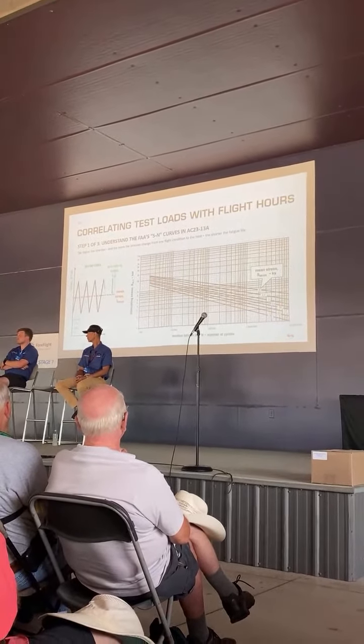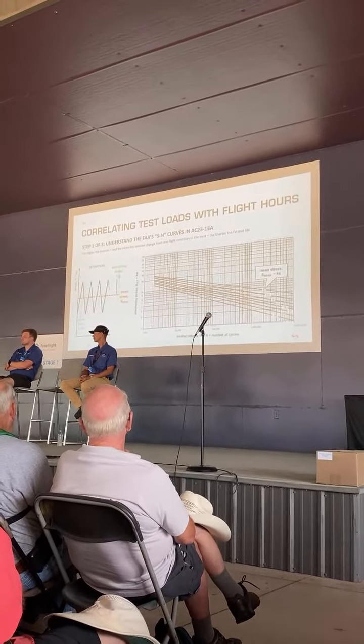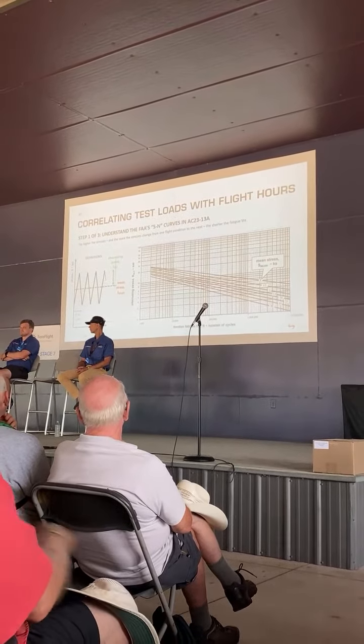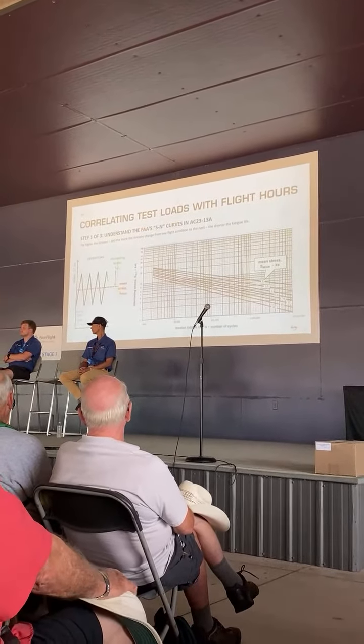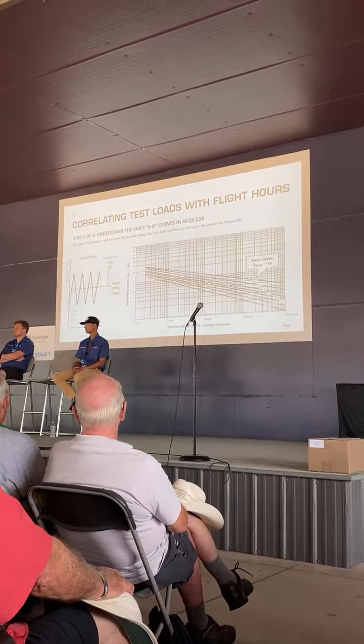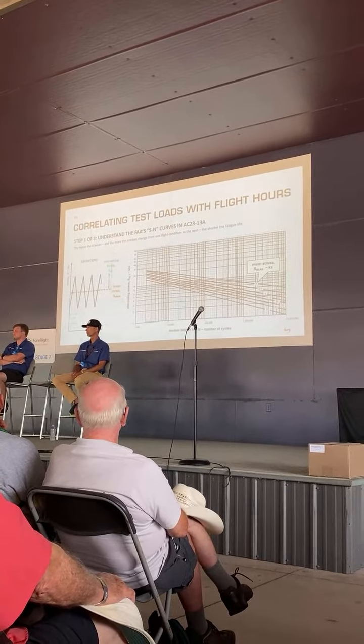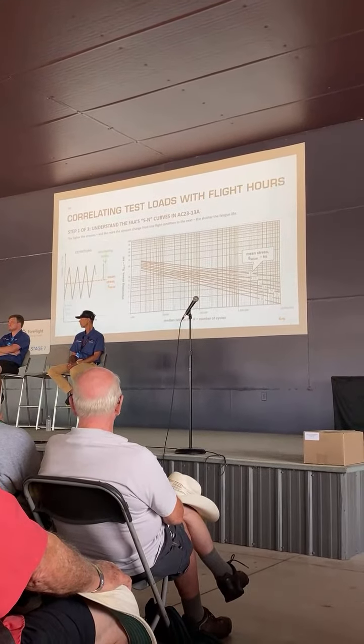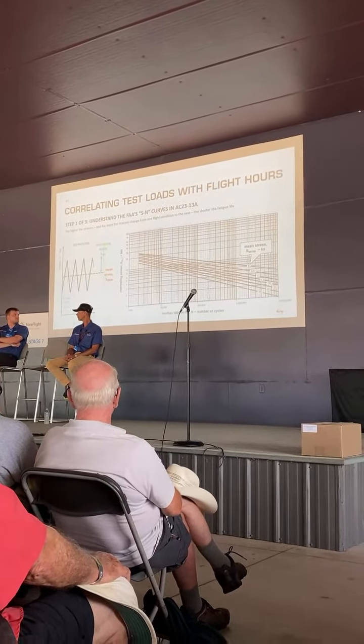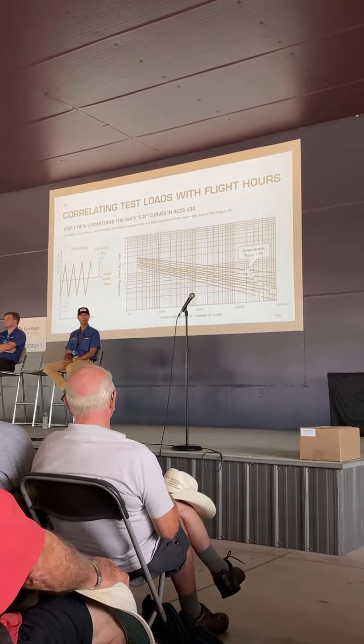So where does all that come from? The equivalency that I was just talking about, 1 hour in flight school is equivalent to 1 one-minute load cycle. This is AC 23-13A, which talks about fatigue testing and failures in aircraft. And here these are lines that are representative of the aluminum that we use in the airplane. This is a logarithmic scale. So these numbers are gaining here by the log, and you're going from 10,000 to 100,000 to a million to 10 million. So if you had this on a linear scale, it would actually be a curve that looks like that.